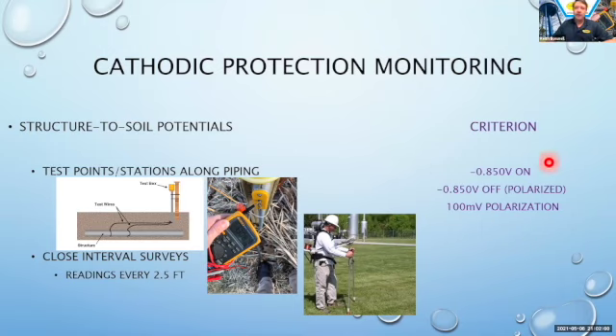Criteria that are utilized within the industry to show and prove adequacy of cathodic protection. The first criterion is having a polarized potential of negative 0.85 volts with the cathodic protection on. However, there's some caveat to that potential, because with your cathodic protection on, you have current flowing through the soil, you have resistance of that soil, and so inherently you have some voltage error built into that reading.